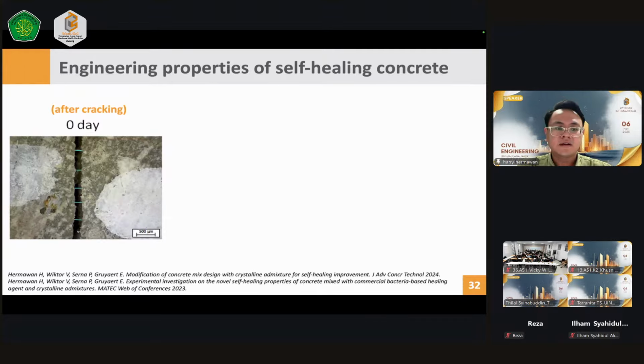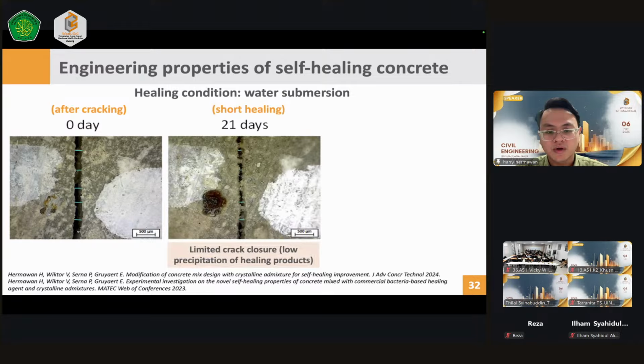And after we try to heal this specimen underwater, what happens? For instance, after a short healing of about 21 days, what's going on? If you see on the crack lines, there was a limited crack closure, with low precipitation of the healing product. You can really compare from the picture on the left and also in the middle part.